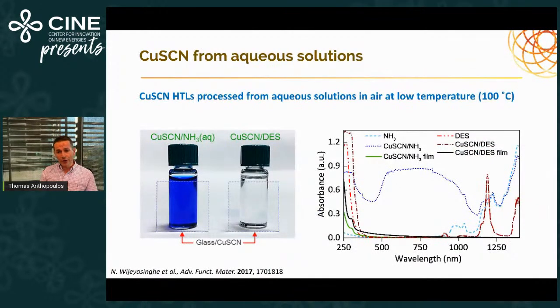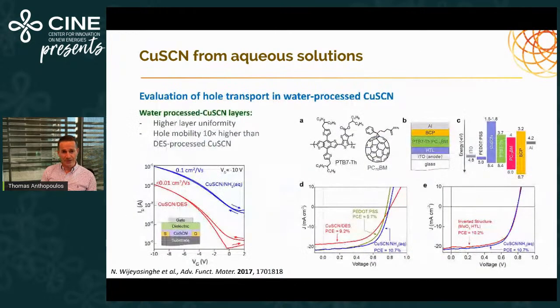We were able to overcome the difficulties associated also with using sulfur-based solvents like DES. Everything I've been showing you so far was based on copper thiocyanate processed from DES, and now we use aqueous ammonia. So essentially, the moment you dissolve it there, the copper ions dissociate. You see this coloration of the solution to blue, which is classic for copper ions in the liquid.